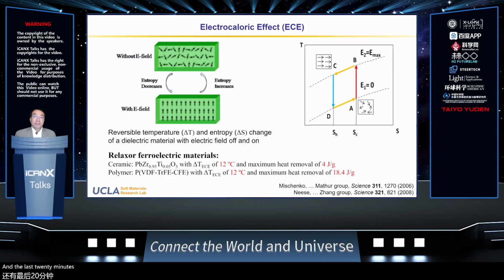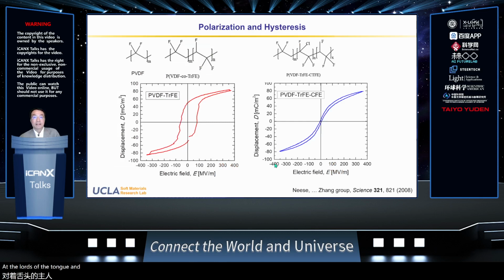And the last polymer I want to introduce is the electrocaloric polymers. We were inspired by the work on relaxor ferroelectric materials, either the PZTs or the PVDF terpolymers. These electrocaloric materials have a large adiabatic temperature change, up to 12 degrees Celsius. When you apply a field to this kind of material, as the dipoles orient, its entropy is reduced, so the material releases a large amount of heat and the temperature goes higher. But when you remove the voltage, the dipoles relax and the temperature goes down. So it generates reversible heating with the voltage on and cooling with the voltage off.